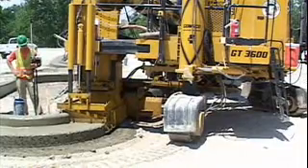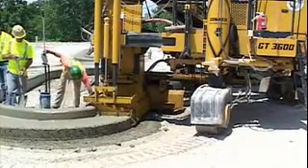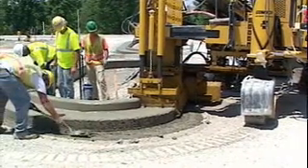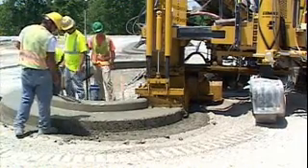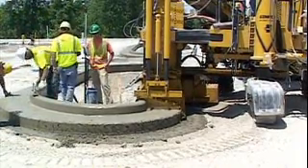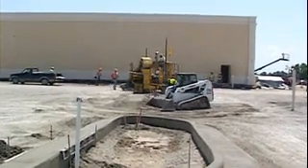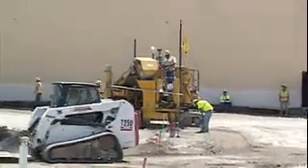On the tightest radii the machine can handle, Kevin noted it really comes down to the machine and the mix design — he thinks the mix design and slump are the bigger challenge. The mix here is running at a two-inch slump, a county mix, a six-bag mix with finish sand. Running with finish sand has helped them out a lot.